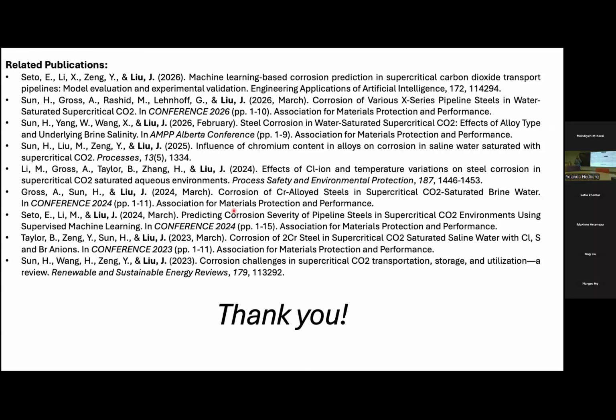I think it will also help if we can design an electrochemical cell for this environment. As you could tell, it's very challenging because of pressure. It's not so much the temperature; it's the pressure. Currently we are mainly focusing on just 8 megapascal, 10 megapascal. I don't have such a cell yet, but hopefully we do. I know people from Norway or Denmark, I forgot, that have a quartz window. They could see it for the CO2 study. Is that for the supercritical? Yes, CO2. With those quartz windows you could see, and they also do electrochemical testing. Actually, it's Estonia.